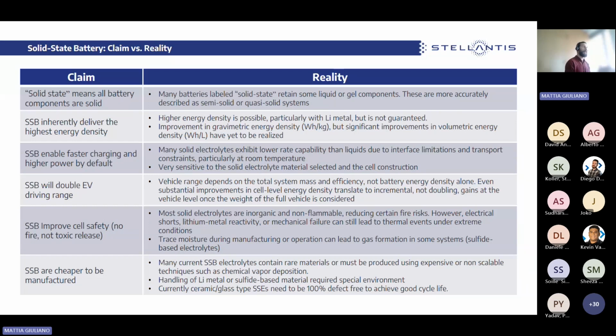In terms of fast charging capability, many solid electrolytes exhibit lower rate capability compared to the liquid electrolyte, and the interface limitation limits the transport and creates constraints for the higher C rate, in particular at room temperature. Another important aspect is that this transport is also very sensitive to the solid electrolyte material applied and on the cell construction.